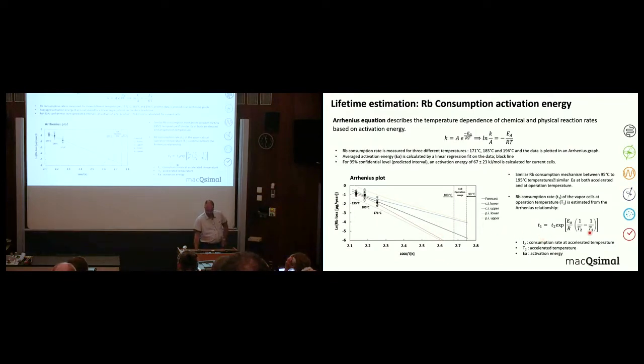So by knowing the activation energy and the temperature at which consumption rate was measured, we can calculate the consumption rate at the temperature where we want to use the cells, which is between 90 and 100 degrees.